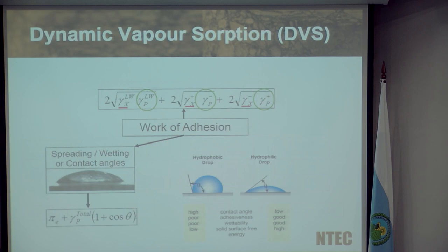The way that we've done it is to take two different approaches. There were five different examples on that previous graph. The way we've done it initially is to take a very simple contact angle approach. The first one is used if we want to determine the aggregate surface energy using an approach called dynamic vapour sorption. On the bottom left-hand corner, you'll see the same schematic that I had previously, where you have a solid material, in this case aggregate, and we are going to bombard it with a liquid, or in the case of vapour sorption, actually a gas, and get that particular probe liquid or probe gas to completely cover the material. If we do that, then by definition, we don't actually have a contact angle.